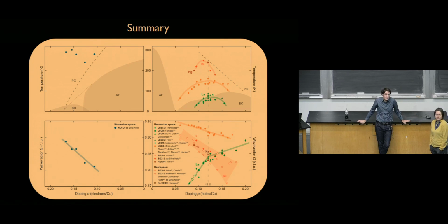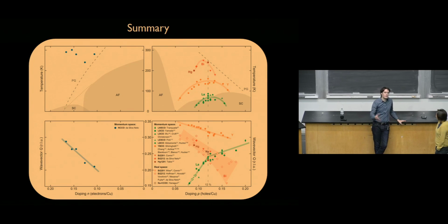One day, maybe the energy resolution will become so good that you can actually see the superconducting gap as a suppression of spectral weight when you do a resonant inelastic X-ray scattering measurement. Now, just to give you the idea, the resolution there is 38 millielectron volts in the best case scenario. So people are starting to inquire about whether you can actually see the superconducting gap in the energy channel as a suppressed spectral weight below the TC.